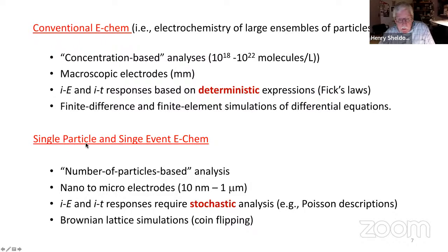In contrast, when you get down to single particle, and this should be single event electrochemistry, instead of working with concentrations, the analysis is based on the number of particles. And frequently the electrode or active area is nanoscale to microscale as opposed to millimeter. And the current time, current potential responses are based on stochastic analyses. Frequently, these processes are governed by Poisson descriptions. And then instead of using finite element or finite difference simulations to model what's going on, frequently Brownian lattice type simulations are used. This is really coin flipping, for instance, to watch a molecule diffusing around or to simulate a molecule diffusing in solution or to simulate if an electron is being transferred at the electrode surface.